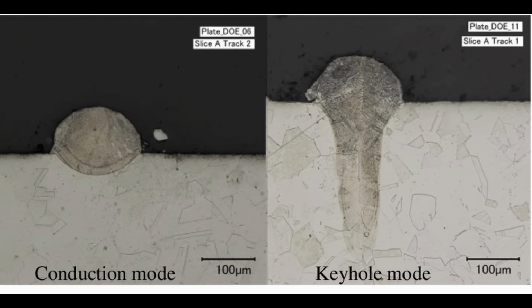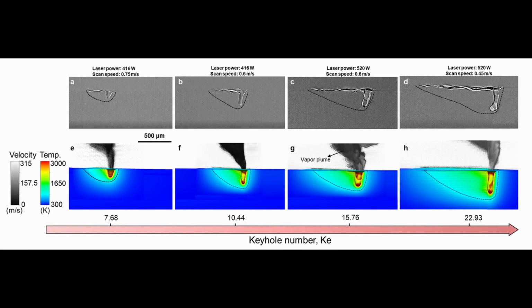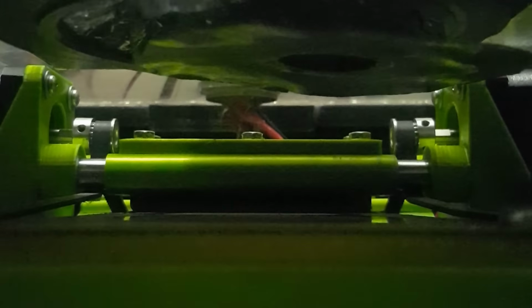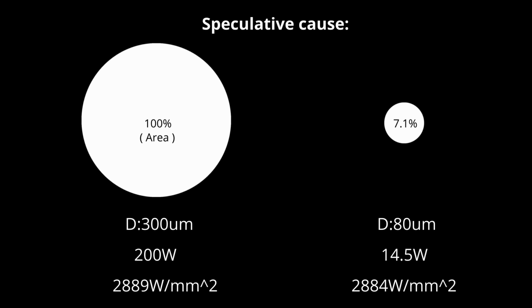With a spot size of 300 micrometers, I could achieve a theoretical power density of approximately 2900 watts per millimeter squared. Plenty enough to create a cohesive bead, but far from the threshold of keyholing, which begins at around 10,000 watts per millimeter squared. Since my efforts were operating well outside the window where there would be enough back pressure to create a cavity beneath the plasma, I was a little unsure of why I was seeing what I was seeing. At 300 micrometers, the spot size is anywhere between 14 to 36 times that of a professional system, so it didn't have the intensity, but it had the volume.